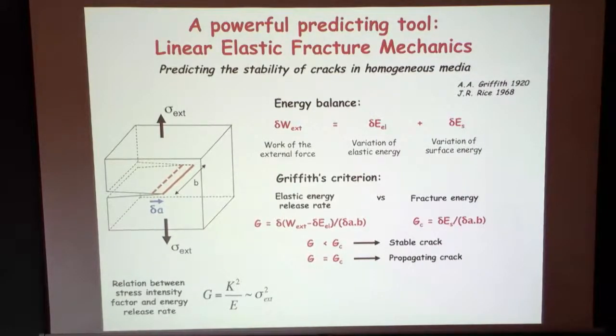Now, when that breaks down, which could happen in very plastic materials, suppose the material deforms at scales where you don't have the square root singularity, then it's a tough material. It's a material that you use to build bridges and whatever, steels and stuff. A brittle material is one that allows the singularity to develop. And then you can use this asymptotic expansion to calculate all of this stuff. Not really trivially, it's tough, but it can be done. But you can do it even for the tougher things. All that's different is in one case you have a really wide region that's plastic, and in the other it's really small. But to push this forward, you still need the assumption that the singularity exists, that it's the dominant term in the stress field.